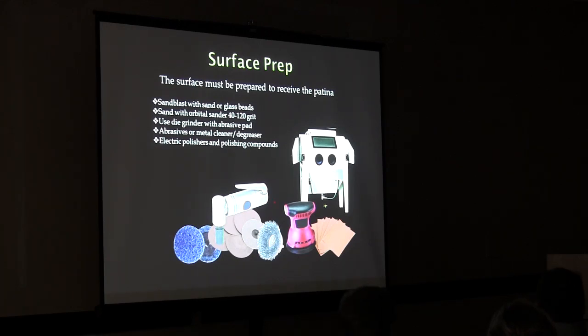And if you're getting into more exotic surfaces, such as something that's semi-smooth or smooth, you might want to go to a side angle grinder there. I do two things if I'm going to do something that's got transparency in it, on steel or on bronze, brass, or copper. I'll do the sandblasting first to get the pits. Then I'll go in with a wire brush on maybe a side angle die grinder.